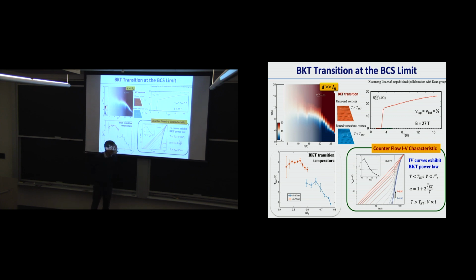Each colorful graph is one density, and then you do the thing for another density. So an important part is we are staying at filling factor total equal one-half, filled Landau level. This means that as you change the magnetic field, the degeneracy changes, so I have to follow that with the density, keep changing the density to stay at this half-filled Landau level.